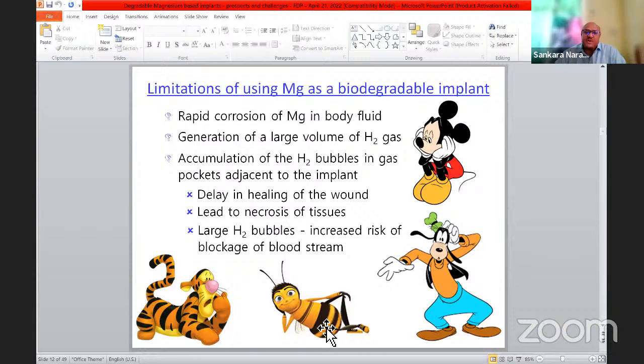And during that process, when there is a dissolution of metal, the side reaction is evolution of hydrogen. So when it rapidly corrodes, there is a large volume of hydrogen gas. And if you are using magnesium as a stent material, there will be accumulation of hydrogen bubbles in gas pockets adjacent to the implant, and that would delay the healing of the wound. It could lead to necrosis of the tissues, and if the size of the hydrogen bubbles is large, that could increase the risk of blocking. When you are putting it in the heart arteries, there may be a blockage because of the hydrogen bubble evolution.